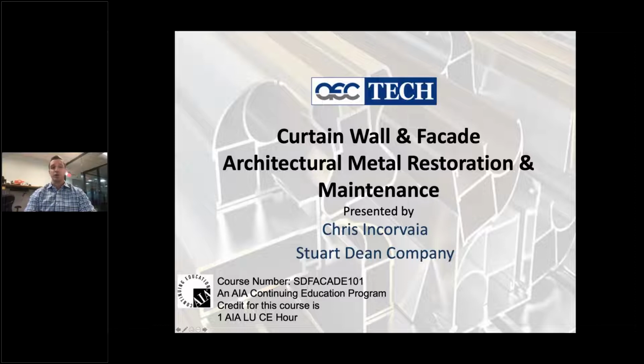If you fast forward to today, the standards have continued to lessen and lessen from where they were in the 1950s and 60s. Today, a typical piece of aluminum for an exterior grade goes in the vat for 17 minutes, and it comes out at 0.8 mils. The importance of that 0.8 mils, we'll show shortly, is that there's a baseline or minimum for performance. On the interior, there's much less need for the same level of thickness as the aluminum isn't exposed to the elements and the harsh conditions of rain, acid water, or UV from the sun.